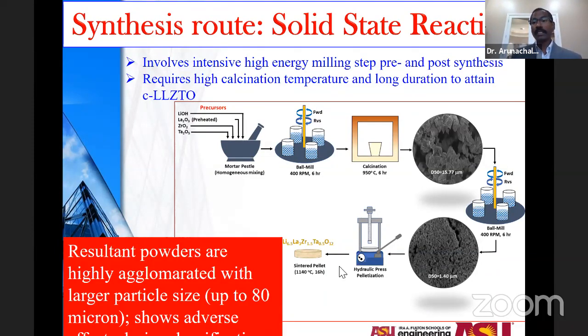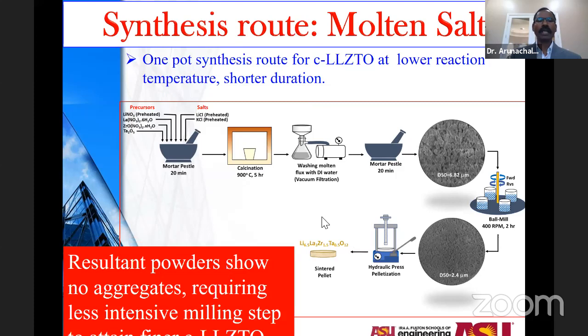So you might ask, if the particle size is larger, what happens, right? If the particle size is larger when it is made, after we make the pellet and then densify, the pellet cannot reach a higher density of above 95%. That means the particles have to be broken into relatively finer form to have the required pellet densities. So this is again a similar, but one-pot method.